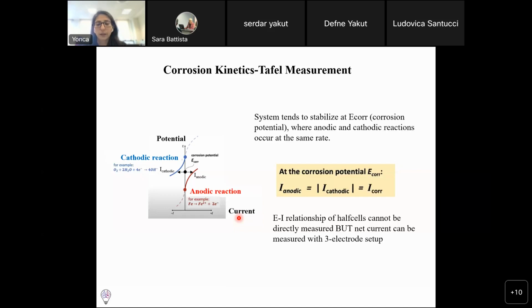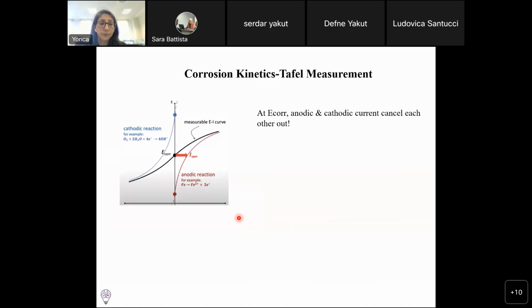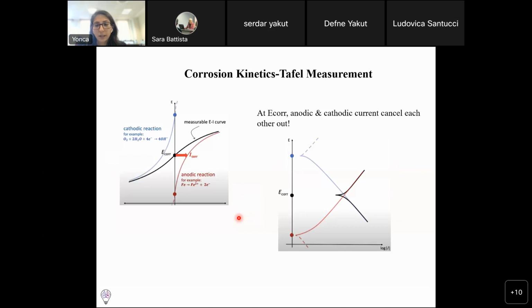So it's quite impossible to have a direct measurement of the potential and current relationship of these half cells individually, but we can measure the net current by using a 3-electrode setup, and this is what I did in the study. At corrosion potential, the anodic and cathodic currents cancel each other out, but let's plot this on a logarithmic x-axis. Be careful, here you have the logarithmic current in absolute values, and you have the potential, and the cathodic and anodic parts. At the point where they intersect, you have the corrosion current.